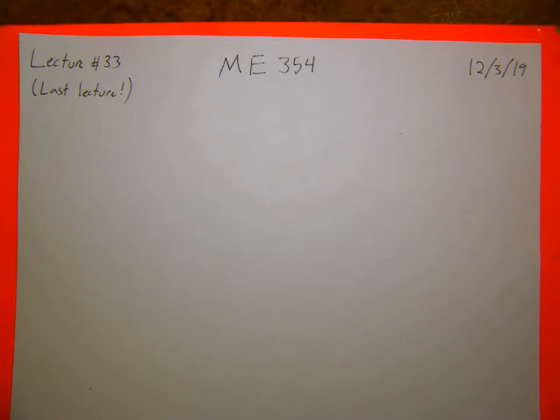So that means the applied stress on the sample is actually matching up with the strain that we're seeing axially in the far field. The strain, however, at the edge of the hole is where a lot of that error is coming in. So here, we're at the start of the plastic yield point for the specimen, which means the whole gauge section of the sample is starting to plastically deform. But that means the stress at the edge of the hole is three times-ish what the stress in the body is. Different because of the boundary conditions, but somewhere around that order.